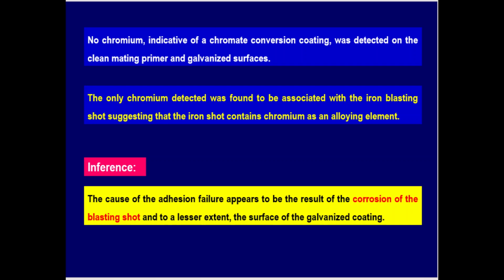Inference: the cause of the adhesion failure appears to be the result of corrosion of the blasting shot and, to a lesser extent, the surface of the galvanized coating.